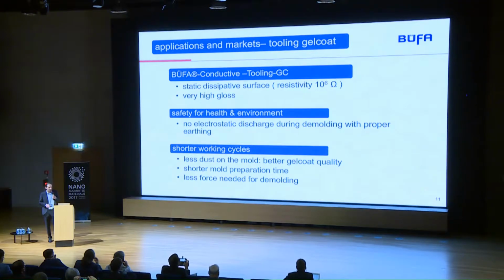Why do you need a conductive tooling gelcoat? Because standard unsaturated polyester materials are insulators. They are non-conductive, and if you demold the GRP part from the mold, you always have electrical discharge, and the reason is a triboelectric effect. And we made a tooling gelcoat. This is the surface of the mold with a surface resistivity of 10 to the power 6 ohms per square. This is enough to transport every electrical charge from the surface to the earthing point.